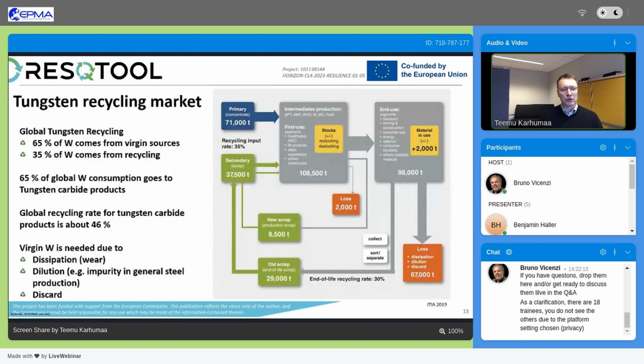Then we come to the tungsten recycling market. This is a study from ITIA, the International Tungsten Industry Association, from 2019, when they found out that the global tungsten production volume is something like 108,000 tons per year. And for this quantity, only 35% of tungsten comes from recycling. So it's really a shame that only 35% of tungsten is recycled.